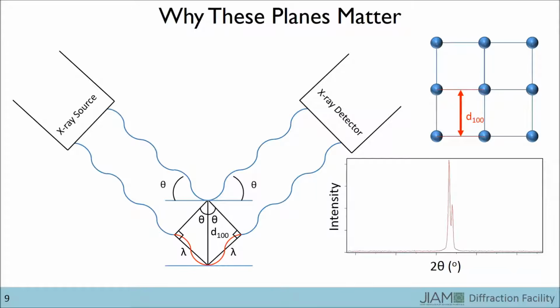Making use of the sine function, the wavelength can be shown to equal the d-spacing times the sine of theta. This only takes care of half of the additional length that the X-rays must travel. Because there is another half, the total additional distance that must be traveled by the lower path is 2 times the d-spacing times the sine of theta, which gives us Bragg's law, the law that outlines the condition that must be met in order to obtain constructive interference and a diffraction peak.